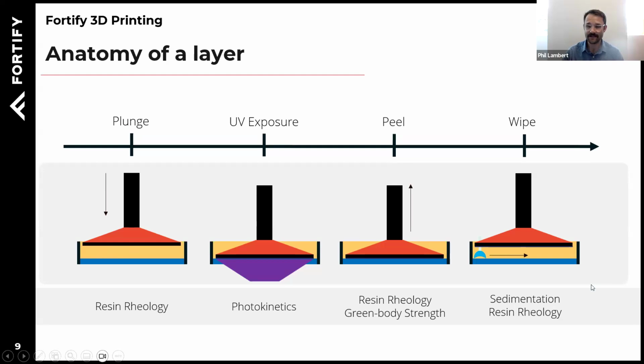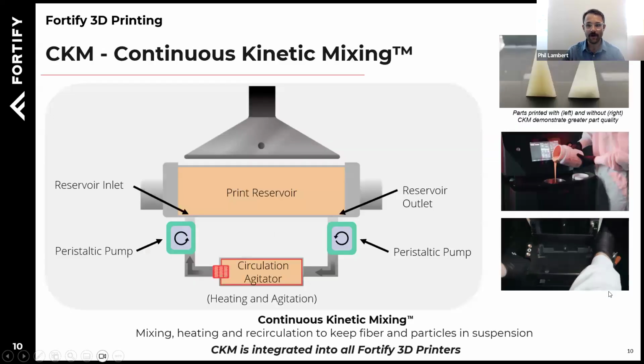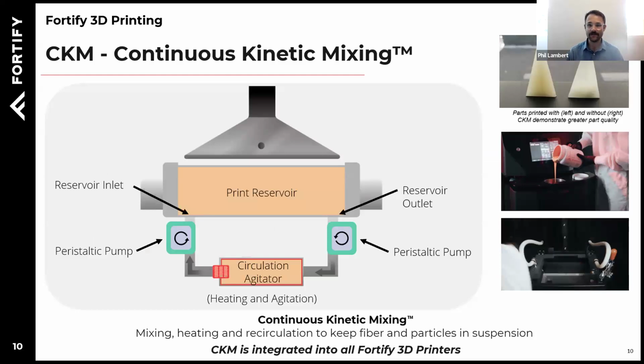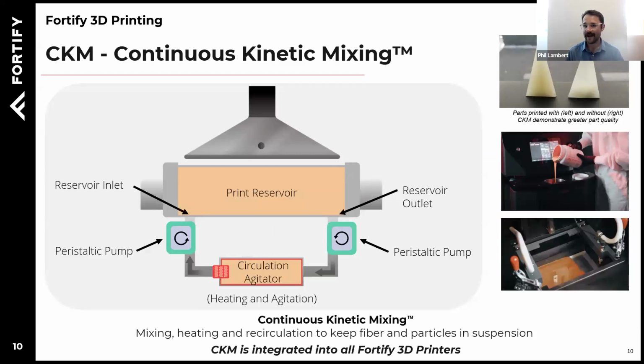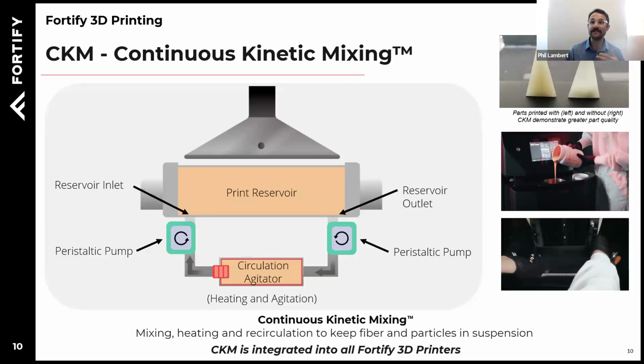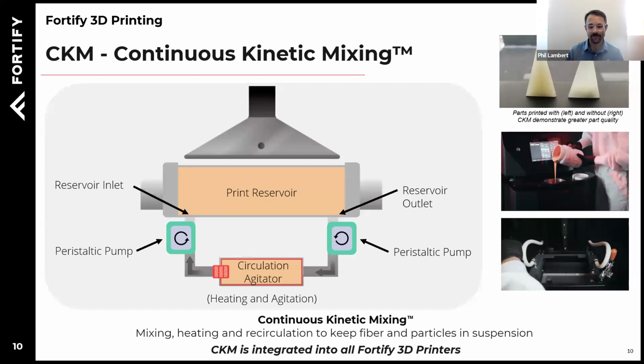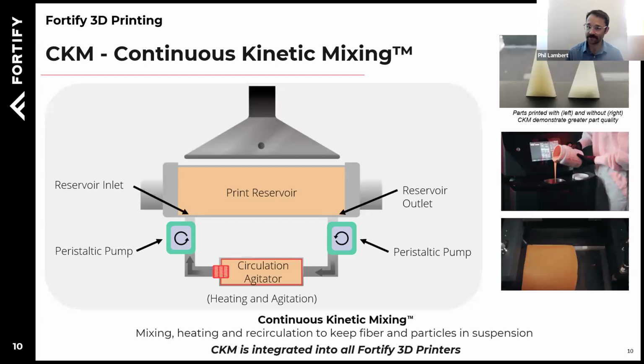We didn't invent this technology. This is a type of 3D printing that has been used across industry for several years now. However, what's unique in our technology is that we print with fiber-filled resins, which means that all of the photo-curing resins that we use are filled with some sort of fiber, particle, or solid additive. We need to maintain the homogeneity and the distribution of those particles in our resin so that our final material properties and our processing characteristics are the same from the start to the finish of a print.